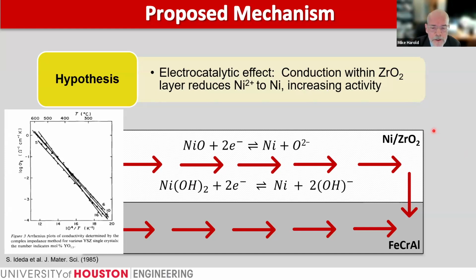As a result, the electrons have the opportunity to do an electroreduction of the nickel oxide / nickel hydroxide to nickel metal. And as I mentioned a few minutes ago, the nickel metal is known to be a more active support for SMR than is the cationic-based nickel. Now, this is a conjecture that we have to prove, obviously, but this looks to be an explanation for the observations I've shown you so far.